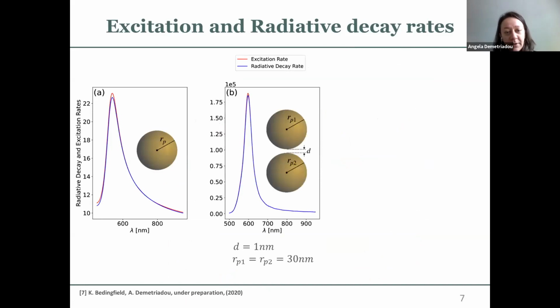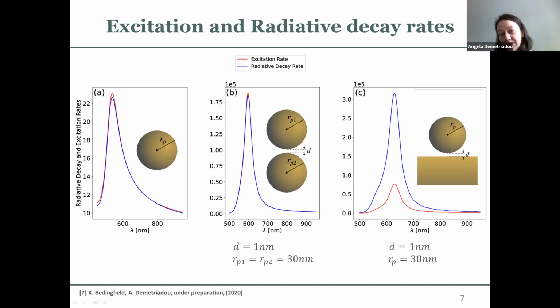We started looking at other similar designs. For example, moving into a plasmonic nano antenna, this is the dimer antenna, taking the same nanoparticle as before. What I'm plotting here is the spectral behavior of the excitation and radiative decay rate. Again, you see for the full spectra, for the isolated nanoparticle, it is almost degenerate. And the same thing happens for the dimer antenna. So it remains degenerate. However, it is different for the nanoparticle on mirror system, where you see the radiative decay rate is about 3 to 4 times stronger than the excitation rate. That means that this system radiates to the far field a lot more efficiently than I can actually couple energy to it and couple energy into my quantum emitter.